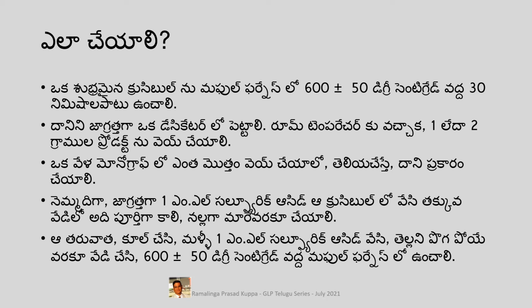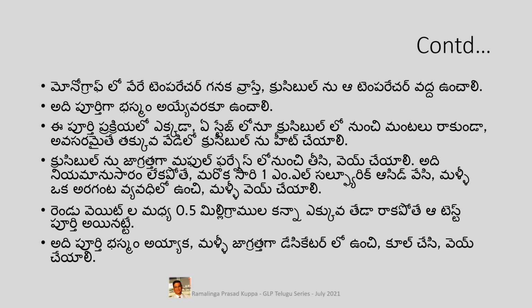Heat it slowly over a slow flame or slow heat so that it becomes totally black. Then add another 1 ml of sulfuric acid. Heat it so that all the white fumes come out completely. Once the white fumes have completely come out, then heat at the high temperature of 600 plus or minus 50 degrees till the entire material is charred completely. Now continue the heating of the crucible at the temperature required till the entire material has totally become ash. If a separate temperature is mentioned in the monograph, do accordingly. And make sure that at any stage of the test there should not be any flames coming out of the crucible.